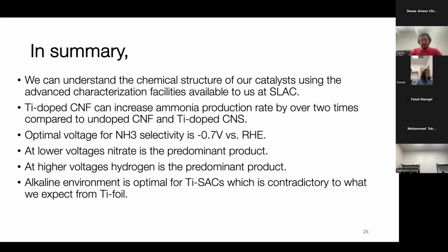We identified that the optimal voltage is about -0.7 versus RHE, which is not very ideal because there are some better catalysts out there. Right now, I'm working with cobalt and copper, and generally you can operate those at 0. So you have a 0.7 volt overpotential there. That is not very good once you start doing technoeconomics. And we can identify the different regimes. So at lower voltages, nitrate is more of the predominant product, and at higher voltages, hydrogen becomes more predominant.